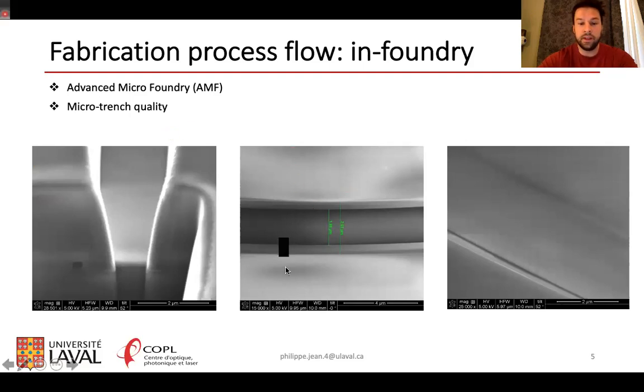Here we can see the fabricated chips. You can see a top view of the microtrench. Here you can see a side view with the sidewall inside where you can see some roughness remaining. And here you can see a FIB cut of the cross-section with the silicon waveguide here right next to the microtrench.